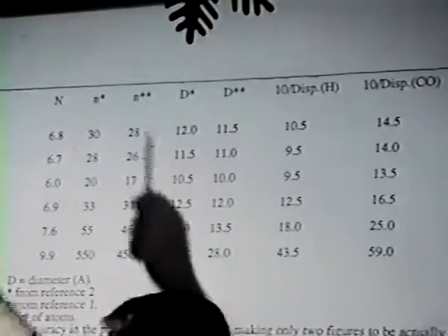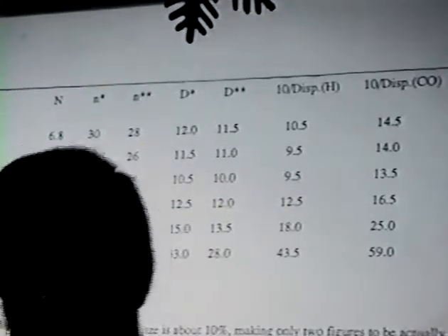In the first one, with one asterisk, you assume that the particles are formed with a face-centered cubic structure where you always put the platinum closest to the center of mass, or another way of putting that, such that it has the highest coordination number. In the second one, with two asterisks, you take into account the interaction of the platinum particle with the oxide surface, and you try to minimize the overall energy. And that changes the number. These are the references where that has been done by this group at the University of Eindhoven. But you see, it's not a big difference, right?